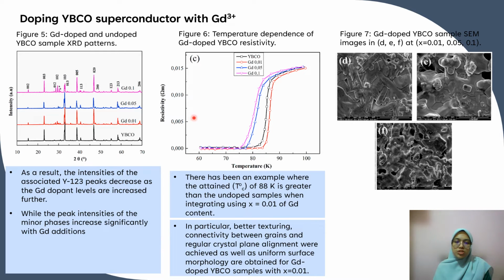Figure 6 shows the temperature dependence of Gd doped YBCO resistivity. There has been an example where the attained critical transition temperature of 88 K is greater than the undoped sample when integrating using x equal to 0.01 of Gd content.